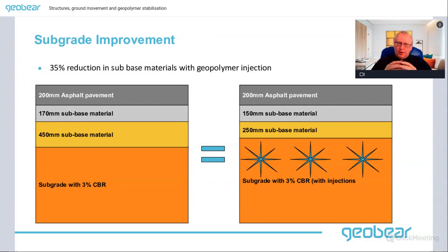Here's an example. So subgrade improvement. This is showing how you could get a 35% reduction in subbase materials with geopolymer injection. So you may have had a CBR of 3% before that required a certain thickness of materials. And if we can inject geopolymer, that is effectively going to raise the CBR, such that you can then use a shallower thickness of material. So this saves money, and in the long run also reduces the amount of materials you're going to need. So it's going to be a lower carbon solution.